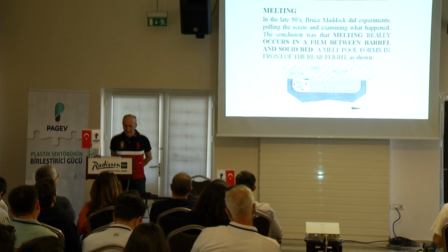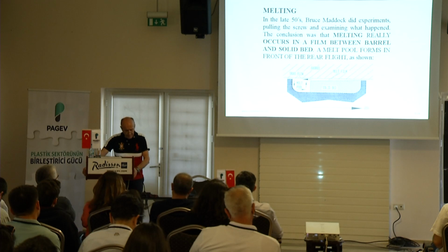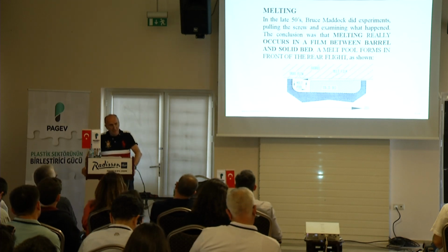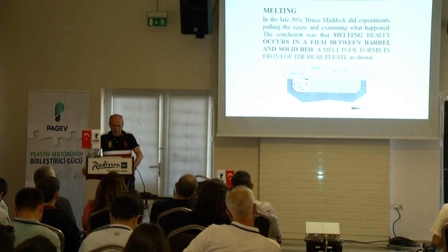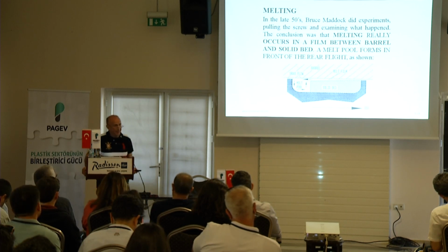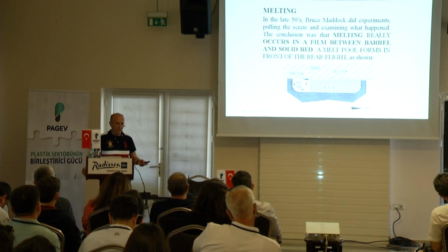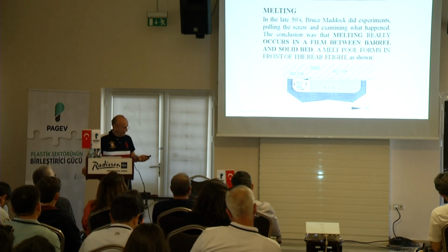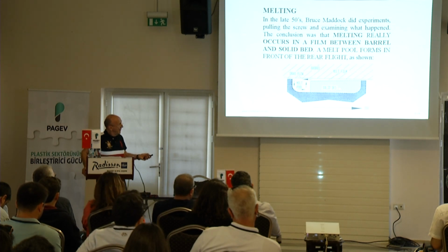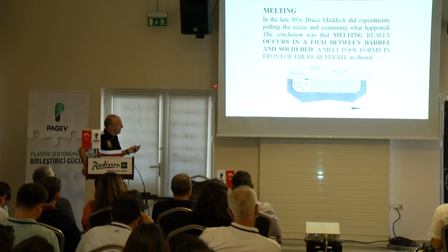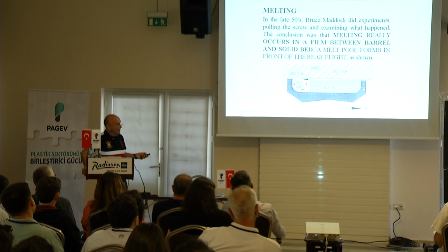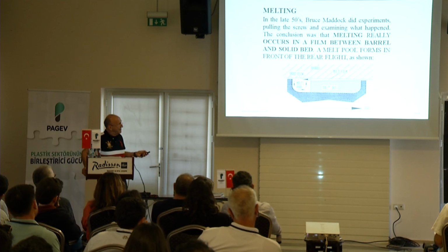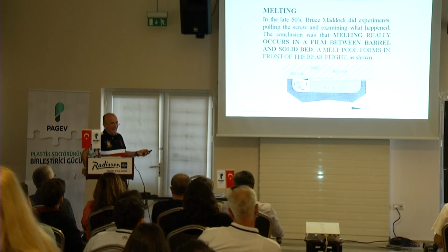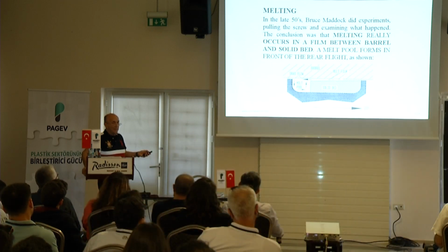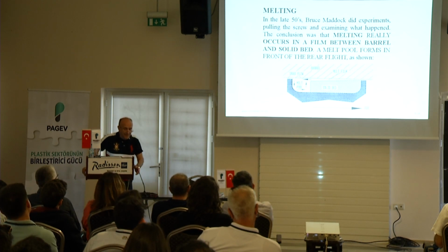Melting. Melting in extruders started to really become understood after the work of Bruce Maddock, who was working at Union Carbide. He did an extrusion experiment. He stopped the extruder, then pulled out the screw and looked at what happened. And he came up with this model. The die is in that direction, and here is the feed on that side. The solid bed, at least ideally, segregates in that sort of flight. Then the melting occurs in a thin film between the barrel and the solid bed, and here you have the accumulation of the melt.